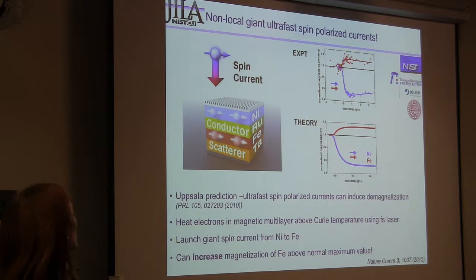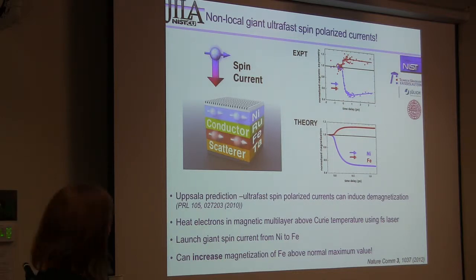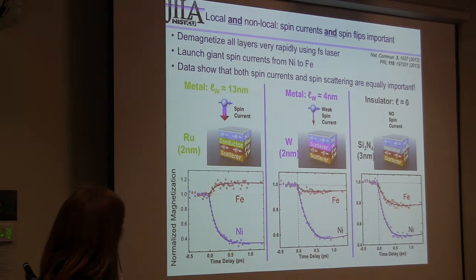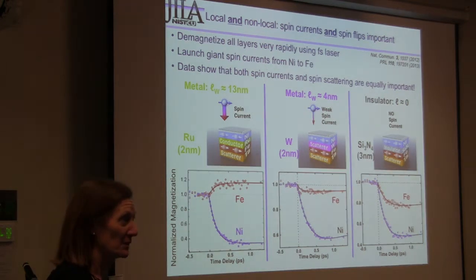A second set, we had already done several, but we did one more, which was instead of having a spin conductor that would let the spins flow from nickel to iron, let's put in a spin insulator. So this is the data I just showed you, if you allow the spins to move between the two layers. But what if you put a spin scatterer or an insulator that won't allow any current? And the insulator is sort of the nail in the coffin, because if you put an insulator and do not allow any spin currents between these two layers, both materials demagnetize.